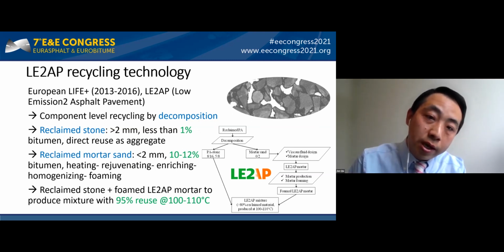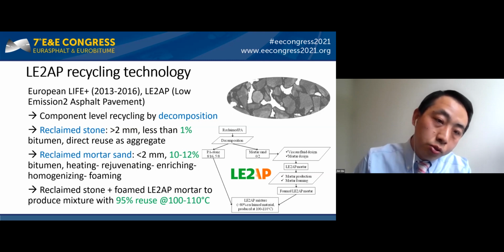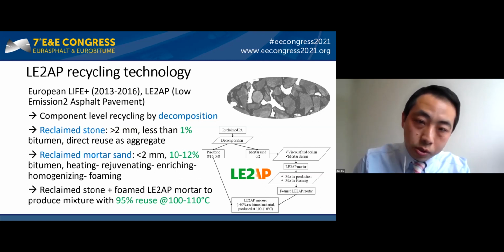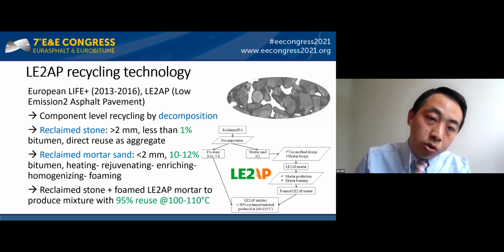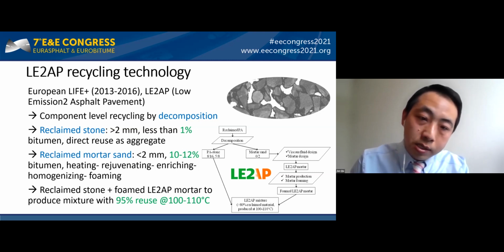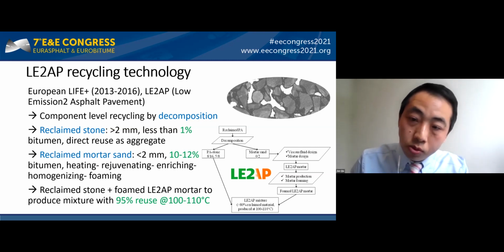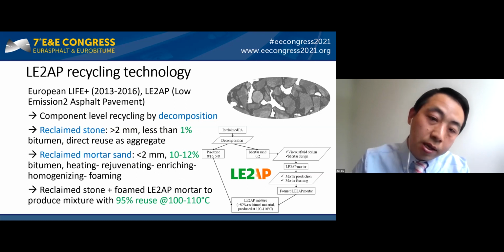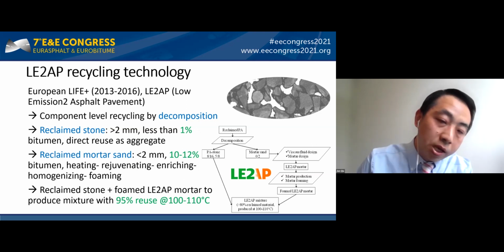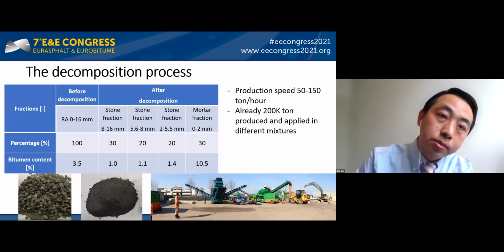The aggregate you can get is with a very limited bitumen content, so you can use it directly as aggregate. The mortar sand contains about 10 to 12% of bitumen. You can do treatment on that, and you're able to have a new mortar sand. Afterwards, you are able to form the mortar and to make a high percentage mix at low temperature.